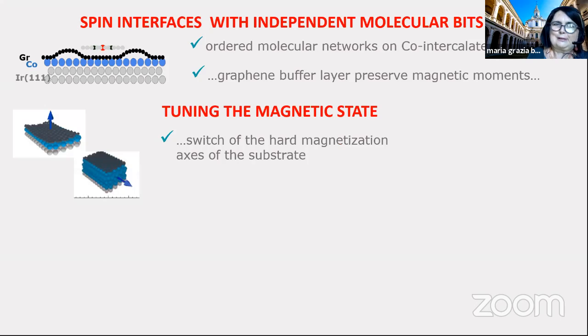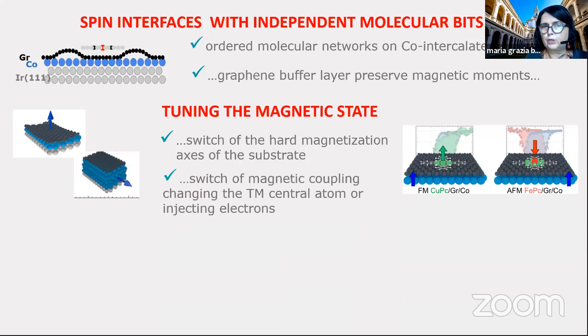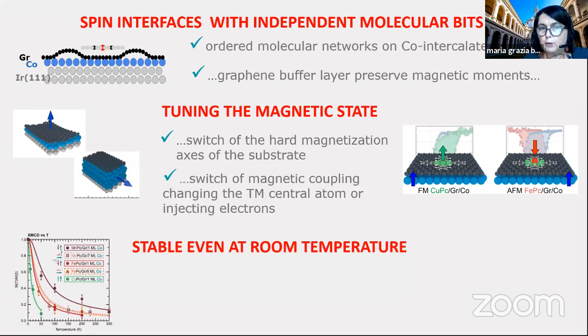Then we can tune the magnetic states of the substrate, changing the substrate and switching the magnetization axis of the substrate. But we can also switch the magnetic coupling, changing the transition metal central atom or injecting electrons. What is most important, all these configurations are stable, almost all, because the ferromagnetic coupling, no, but all the antiferromagnetic coupled configurations are stable even at room temperature.